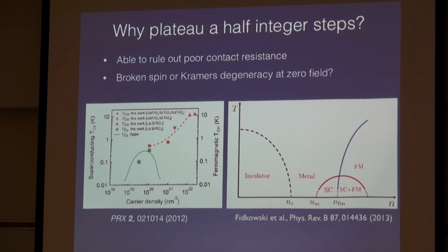But one of the theoretical proposals building on this work has looked at the possibility that your itinerant electrons are pairing in a superconductor, and that there's a whole collection of electrons that aren't mobile. Those are ordering themselves ferromagnetically, and if that were the case, if we had mobile electrons in proximity to a ferromagnetic strip of immobile electrons, we would get a broken degeneracy at B equals 0, and we would observe these half-integer plateaus.